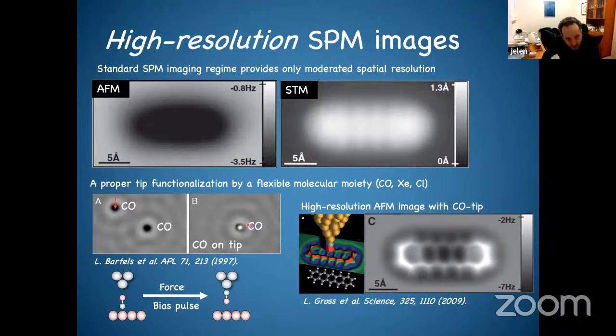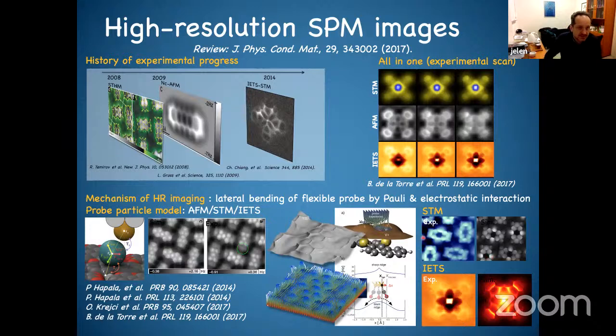And with this kind of weird tip, which is not terminated by an atom but by CO hanging on the apex, when you approach the molecule, now this ovaloid really starts to show the chemical structure. With that, you can see individual benzene rings. These days this technique is very popular, and you can achieve atomic or submolecular resolution in STM, in non-contact AFM, and also with inelastic electron tunneling spectroscopy. So we contributed to the development of this field.